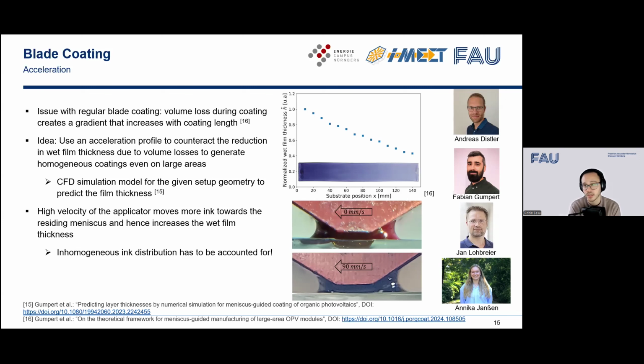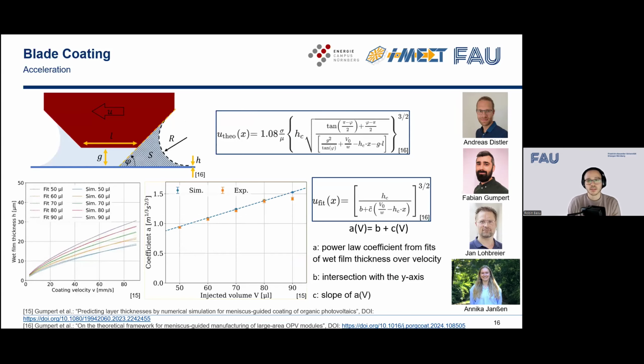And this was work that was mainly done by Andreas Dissler, who is my group leader, Fabian Gumpert, Jan Lohbreier, and Annika Jansen, who was a bachelor student at the Solar Factory of the Future. Some other things that they found: if we go to quite high coating speeds, the meniscus is not symmetric anymore. So we have a shift opposite to the coating direction that has to be taken into account because it directly impacts the thickness of our coating. So those guys came up with a theory based on the CFD models, and we are left with a theoretical formula that allows you to calculate the speed that you have to use at a given point X after the starting point to get the desired thickness.